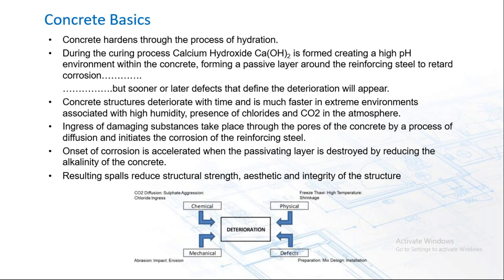Ingress of damaging substances takes place through the pores of the concrete by the process of diffusion, and that really starts to initiate the corrosion of the reinforcing steel. Onset of corrosion of the steel is accelerated when that high pH condition or that passivating layer around the reinforcing is destroyed by reducing the alkalinity within the concrete structure or within the concrete matrix itself. So that then the steel corrodes, then creates a concrete spall, and that ultimately reduces the strength, aesthetics, and integrity of the structure. So that's pretty much it in a nutshell.